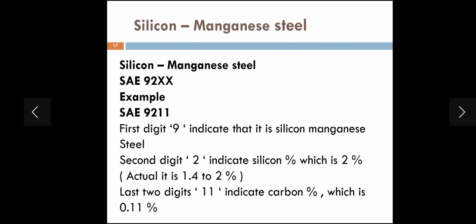Now silicon manganese steel. SAE 9211 is a silicon manganese steel grade. Here the first digit 9 indicates that it is a silicon manganese steel. The second digit 2 indicates silicon percentage in the steel, so 2% of silicon. And the last two digits 11 indicate the carbon percentage, so 0.11 is the carbon percentage in the steel.